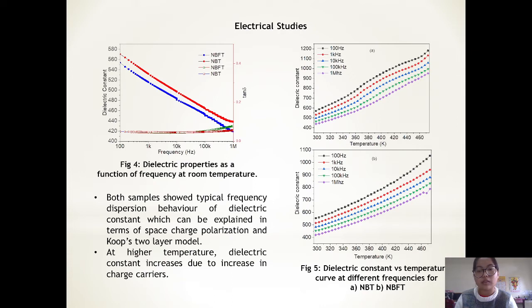Figure 5 shows the dielectric constant versus temperature curve at different frequencies for the two samples, and we can see that at all frequencies, as the temperature increases, the dielectric constant increases. This may be due to the thermal activation of charge carriers at higher temperature.